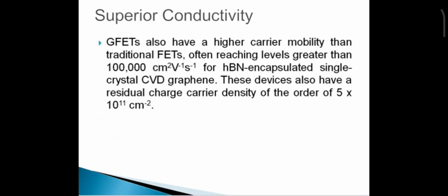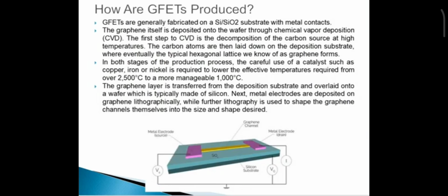Another advantage of graphene is the superior conductivity. Graphene field effect transistors also have a higher carrier mobility than traditional field effect transistors, often reaching levels greater than 1 lakh (100,000) cm²/V·s for hBN-encapsulated single-crystal CVD graphene. These devices also have a residual charge density on the order of 5 × 10^11 per cm². Now the most important part is